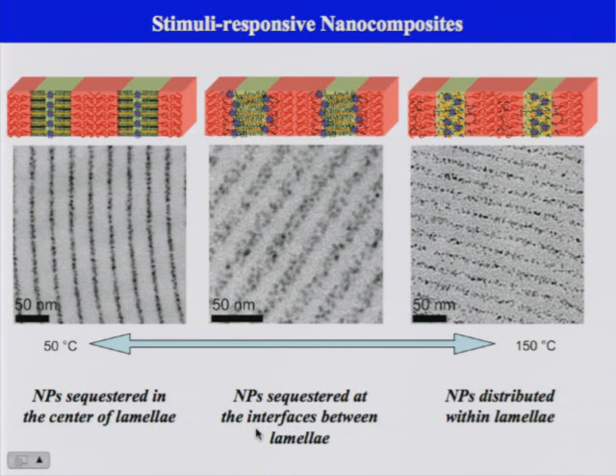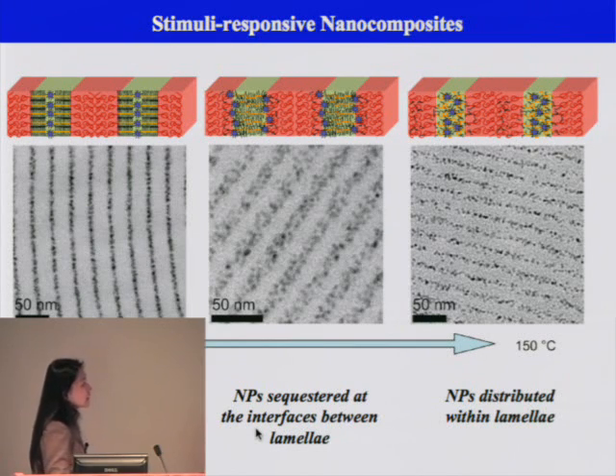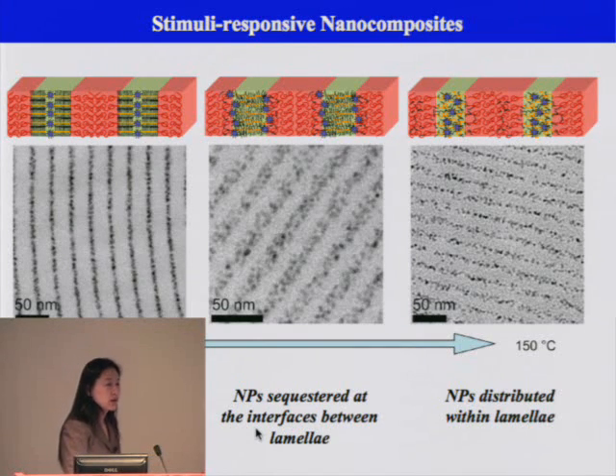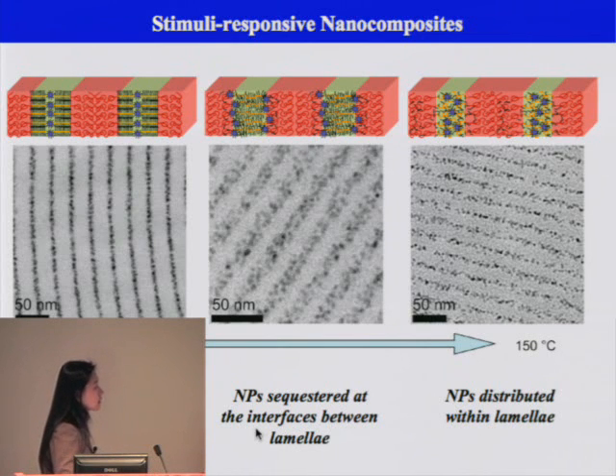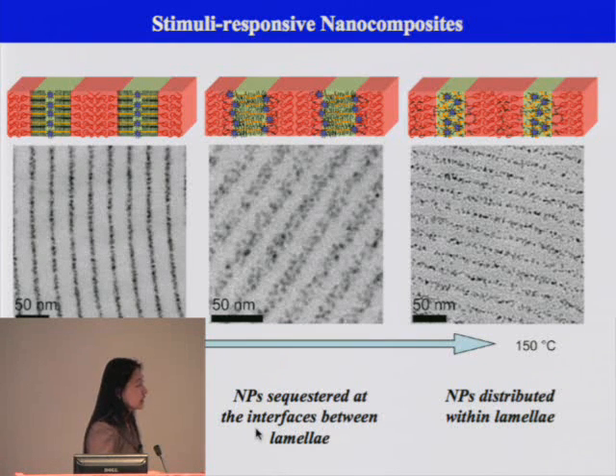By changing the property of the small molecule we're using, we can easily tailor between three different morphologies in a controlled manner. In this case, the particle assembly distance is about 34 nanometers, in this case about 15, and in this case you go back to about 25.